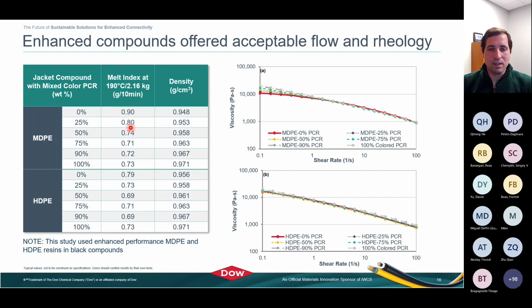And again, melt index and density, noting that in this case the densities of the compounds are higher just because of the starting source of PCR that was available to us. Obviously, there are other sources, and we can tailor or optimize based on targeted densities. Here we want to show the viscosity versus the shear rate, viscosity on the left axis, shear rate on the x-axis, in a parallel plate. You see very good shear thinning behavior, particularly at the high shear rates, with a little bit of deviation at the lower shear rates.